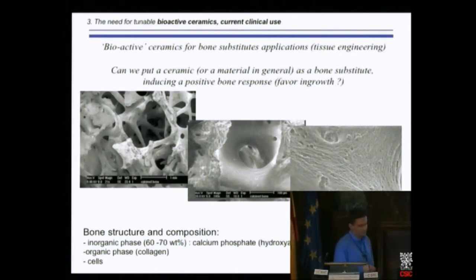So the bone consists, for the mineral part, of hydroxyapatite grains, but at the nano level. So the hydroxyapatite grains in bone are really nano. And concerning the composition, of course, we have an inorganic phase, 60 to 70 weight %, which is calcium phosphate, a kind of hydroxyapatite, to be simple. And also there is an organic phase, which is collagen. And the organic phase plays a great role in the toughness and the energy to failure of the bone.